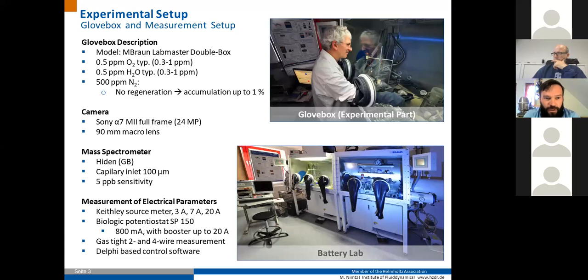The lab also includes a very good camera which we use to observe the experiments. Most of the pictures are from this camera, including a macro lens, because the experiments themselves are much smaller than you would maybe expect. As you can see in the upper picture here, this small white part is actually a liquid metal cell. Steffen is doing experiments right now. And so we mostly have just several square centimeters to look at where all the stuff is happening during charging, discharging, and cycling these cells.